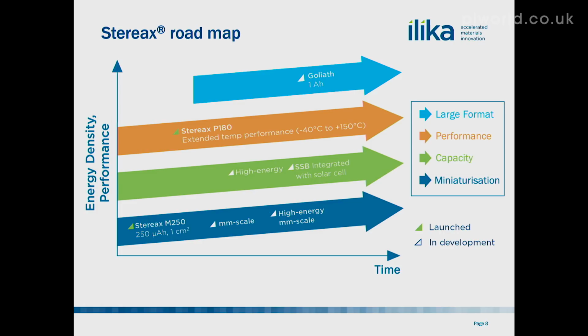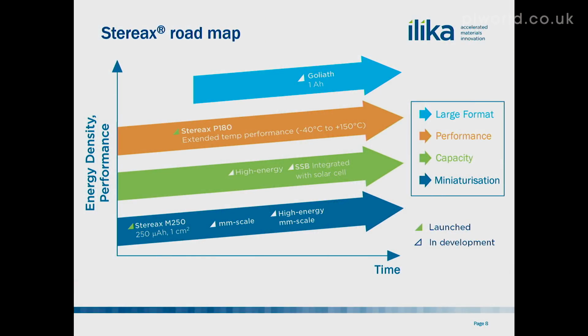There's also, of course, been in the spirit of continual improvement, a gradual improvement of the qualities of some of the launched products. Those of you who follow our news flow will have seen last month that we announced that we've got a higher energy capacity for the M250, which we've achieved by process optimization, so that we've got a greater amount of energy capacity on a square millimeter of substrate. So the M250 has improved in its energy capacity, its energy density as it's sometimes referred to. And then the P180 is one where we've got a high temperature resistance of up to 150 degrees C, which has allowed us to deploy that cell in some quite aggressive environments, such as the automotive industry.